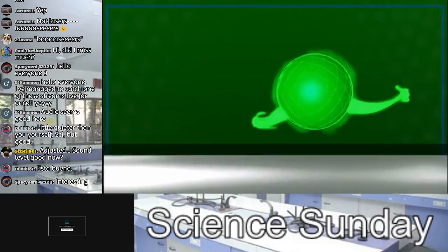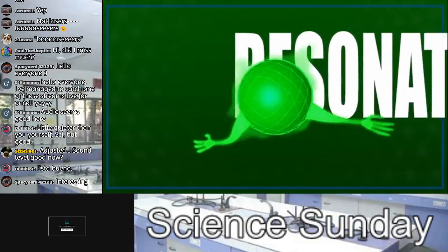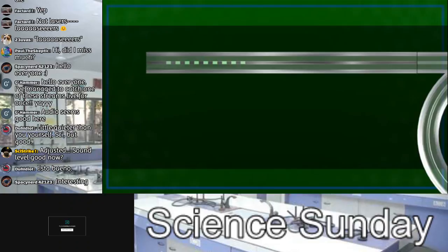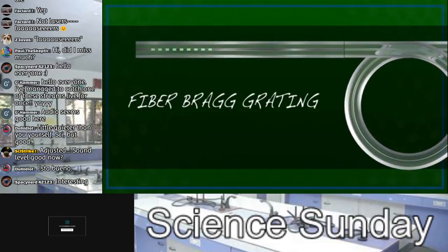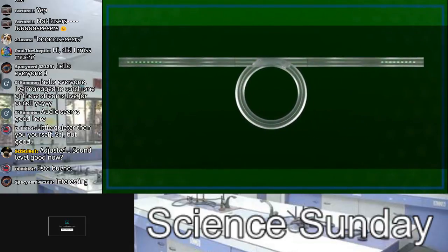To maximize the coordination of the pumping and emission, an ingenious fiber optical cavity, sometimes called a resonator, is constructed. At the pump end of the cavity, a high reflector made using a fiber Bragg grating is spliced to a fiber that is doped with ytterbium atoms. At the output end, a similar fiber Bragg grating with a modest reflectivity of around 10% is installed. Thus, a very simple monolithic single-mode laser device is created.